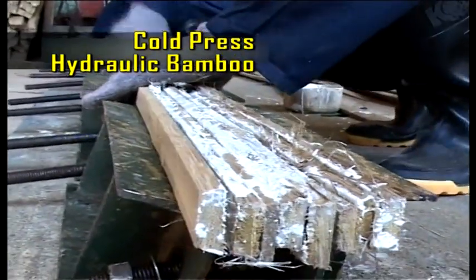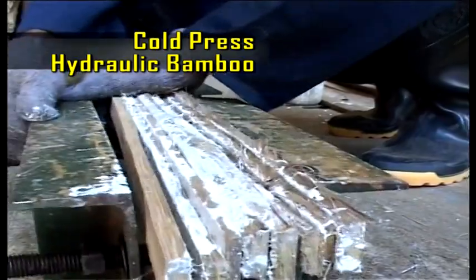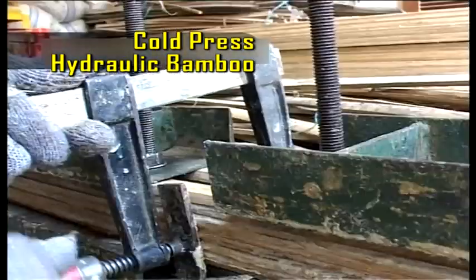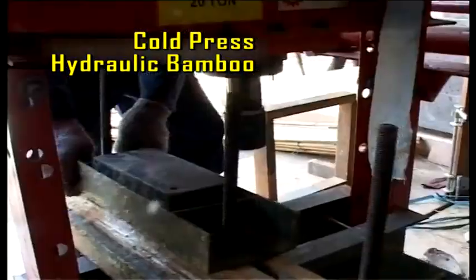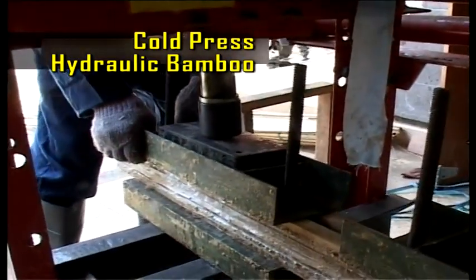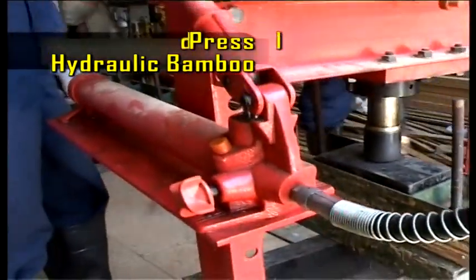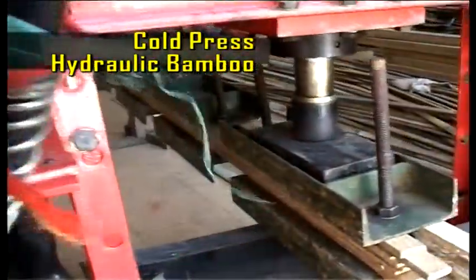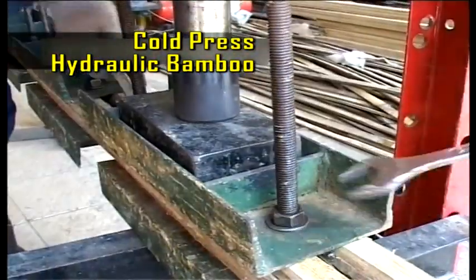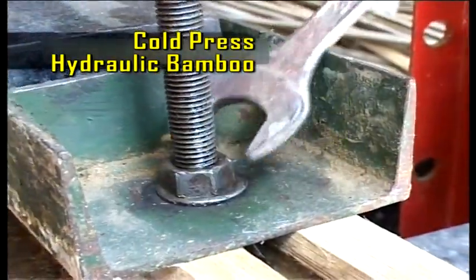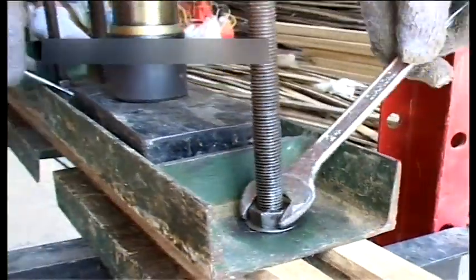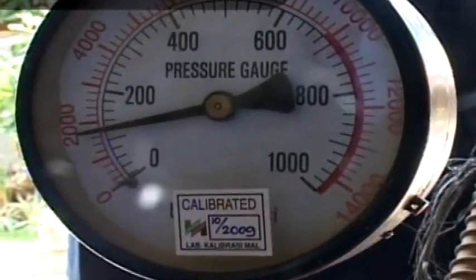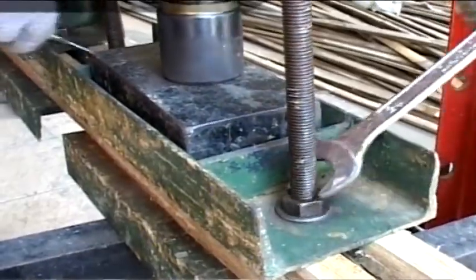Adhesive is then applied to the surface of the bamboo planks, and the bamboo planks are stacked towards the vertical line to reach the thickness according to the size needed. The stripes are inserted into a clamp for a compression process using a cold press hydraulic at a pressure of 2 MPa. In the process of compression, retightening the bolts is needed to maintain the pressure.